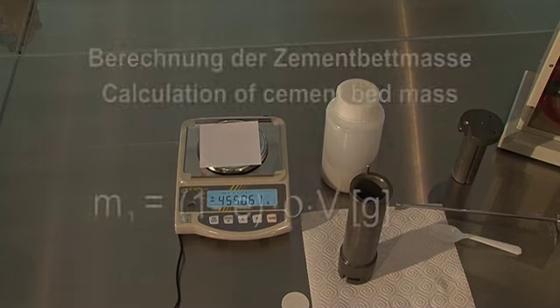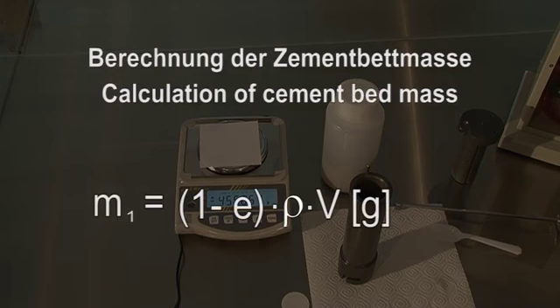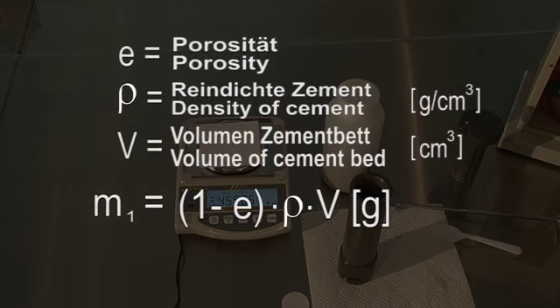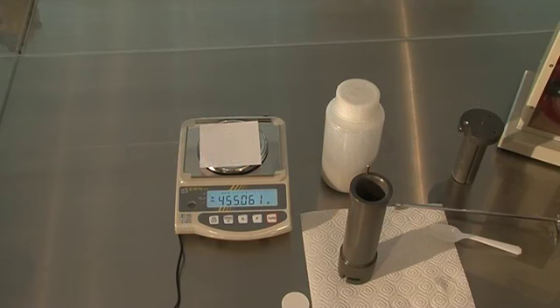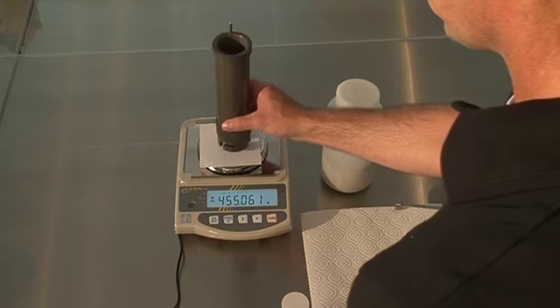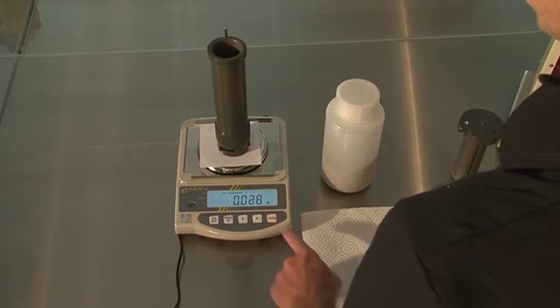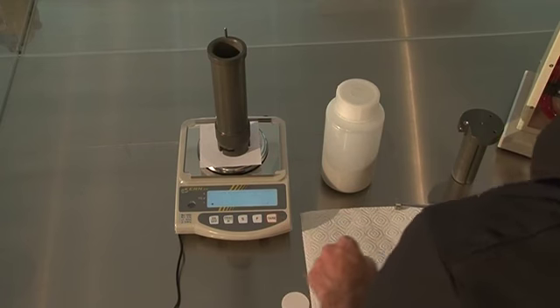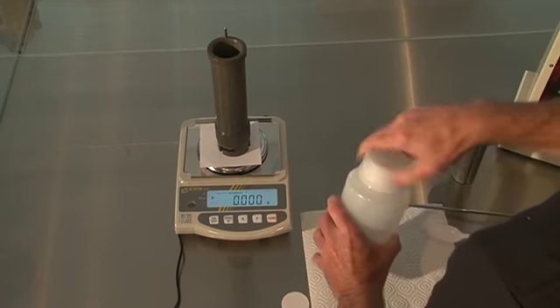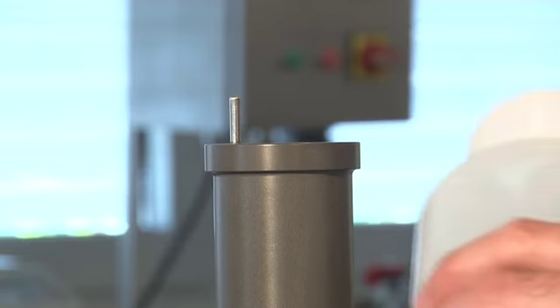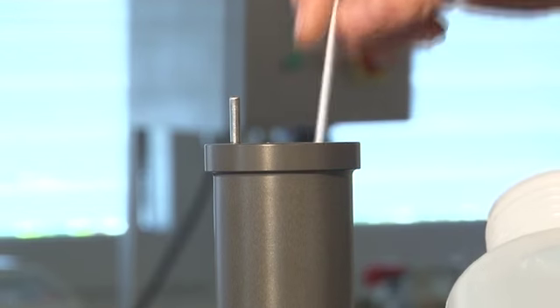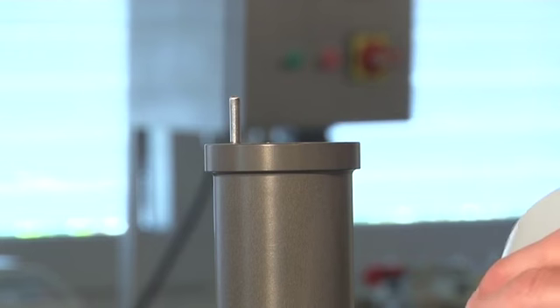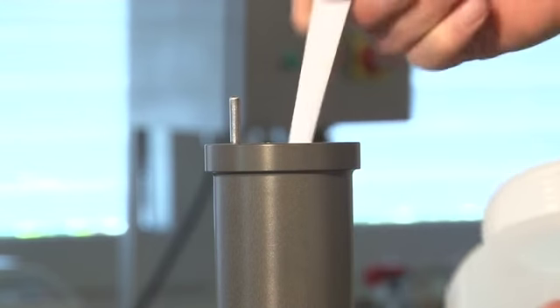The calculation of the cement sample weight takes place according to equation 5, whereby the volume of the cement bed must be known. If this is not known, it must be determined as described in the chapter Determination of Apparatus Constants and calculated. The density of the cement is known or must be determined. The porosity is initially accepted as 0.5. The mass of the previously calculated cement bed is now weighed and poured into the measuring cell.